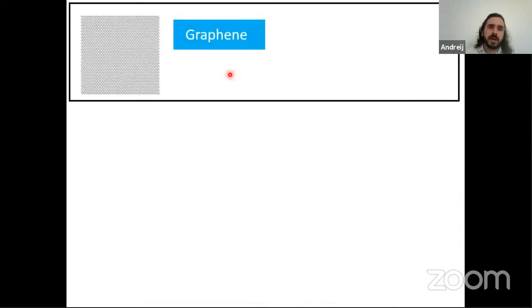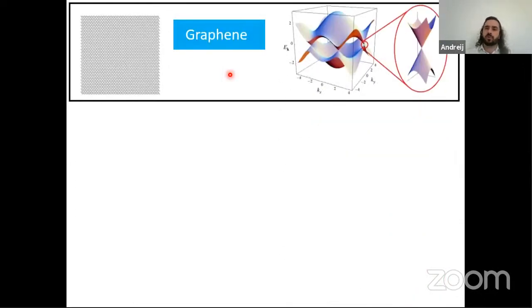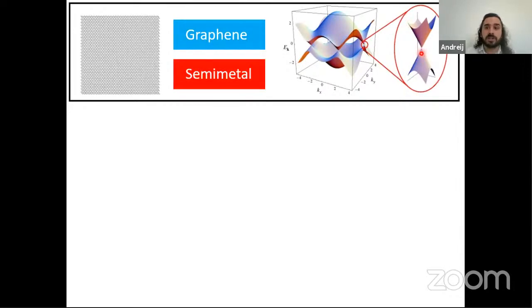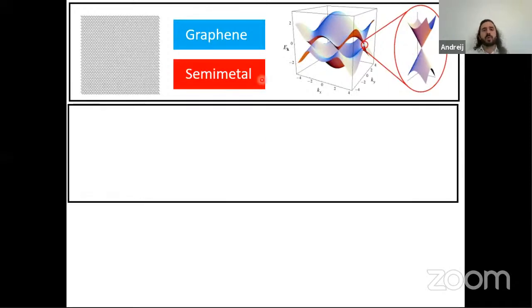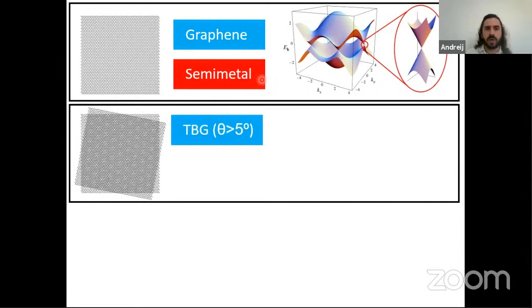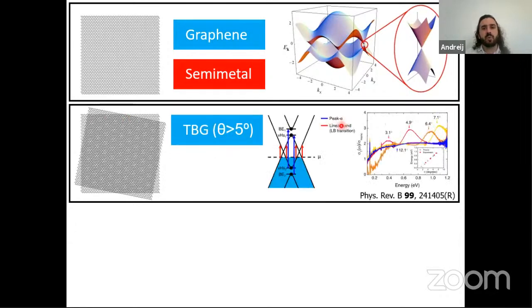But graphene has this specific electronic structure composed of two Dirac cones, okay? And according to this structure, we can say that graphene is a semimetal. But when we go to twisted bilayer graphene with large angles, okay, large angles here are angles larger than 5 degrees, we have not one, but two Dirac cones. And in the intersections between them, it forms some gaps which have optical activity.